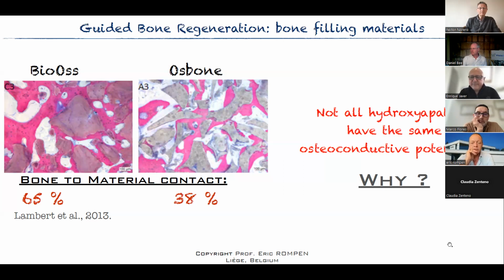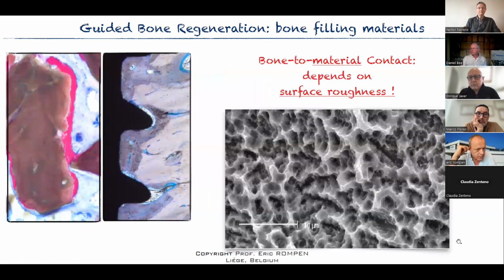Why is that? Why do not all hydroxyapatites have the same osteoconductive potential? We have to think of dental implants. It's not a problem of porosity, it's a problem of topography, of surface roughness. We all know that with dental implants, we have a much higher bone to implant contact with rough surfaces. And it's extremely important also for biomaterials to look at the surface of each particle of biomaterial and check if the surface is rough. With a very high surface roughness, we can really osseointegrate our particles of biomaterial. And bone to material contact depends on surface roughness.